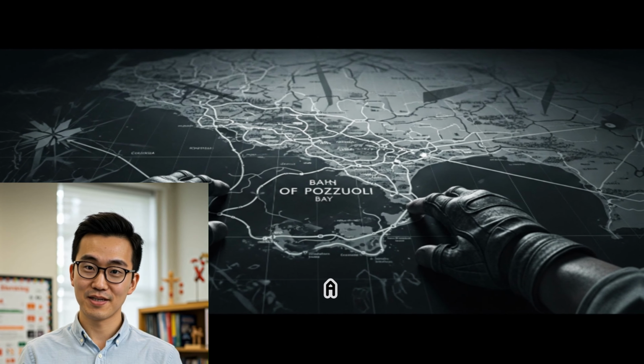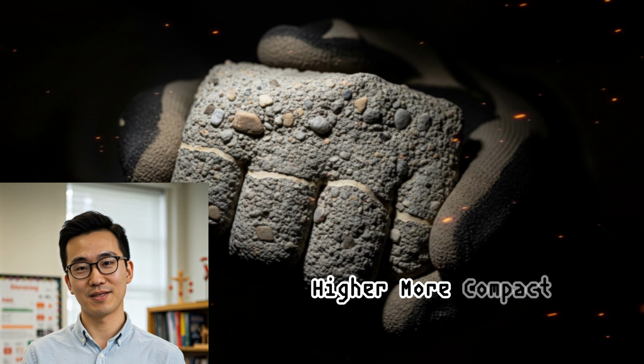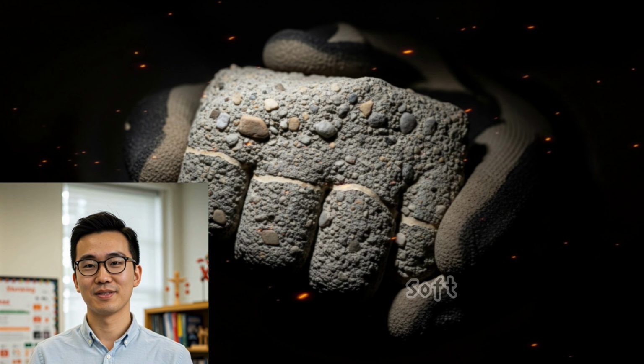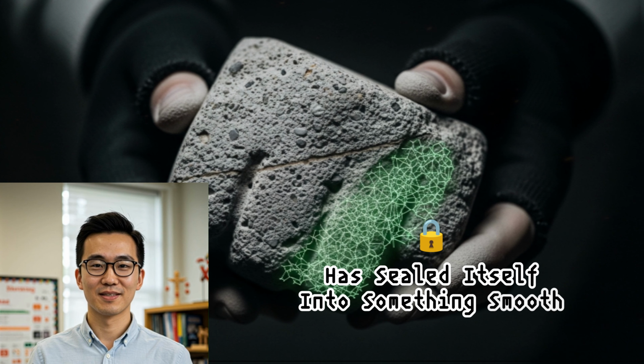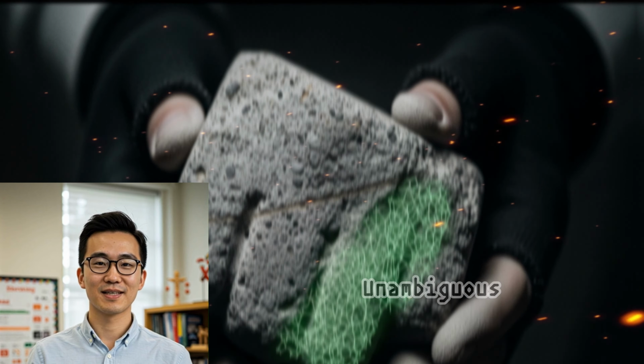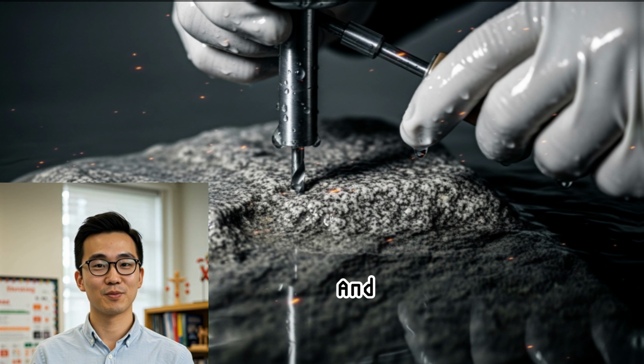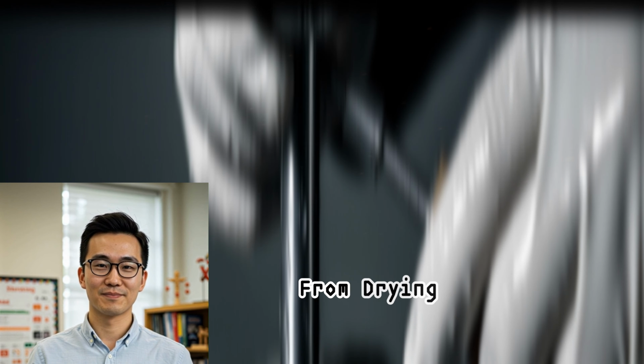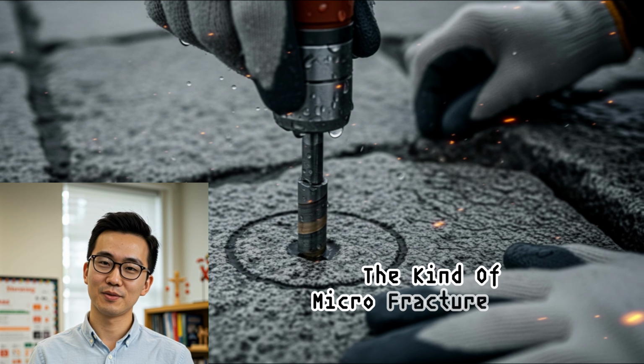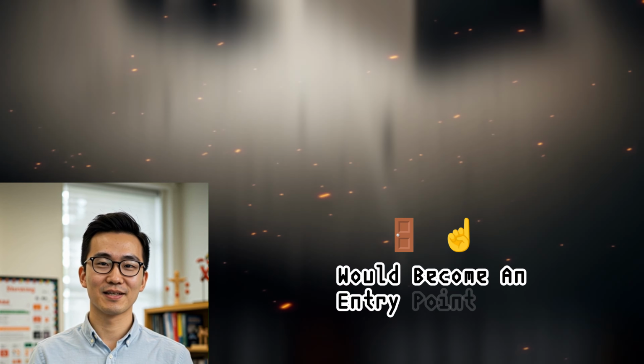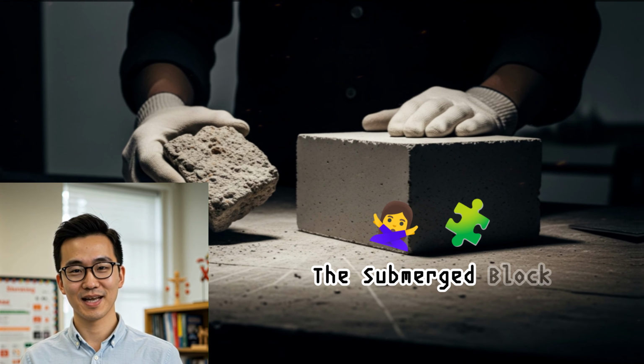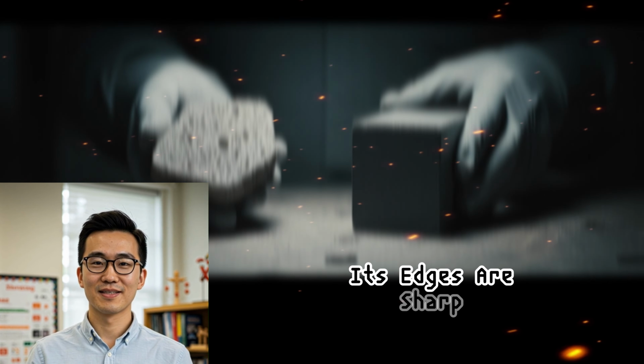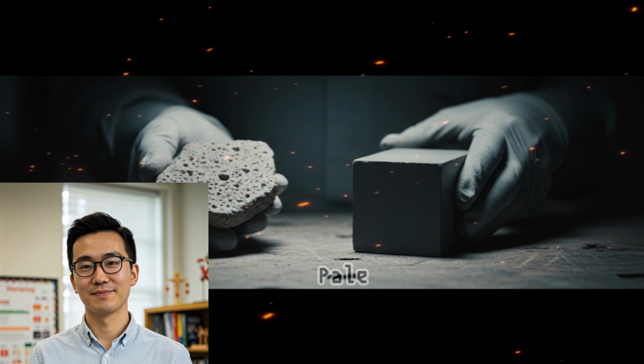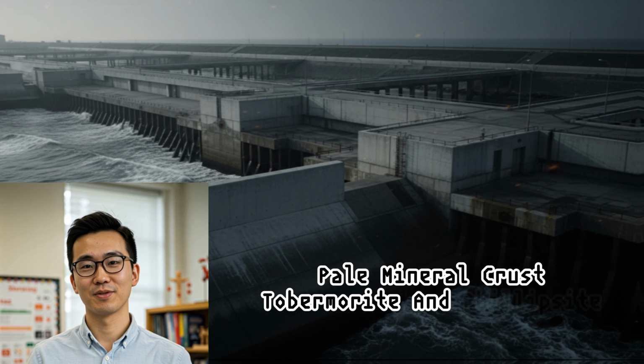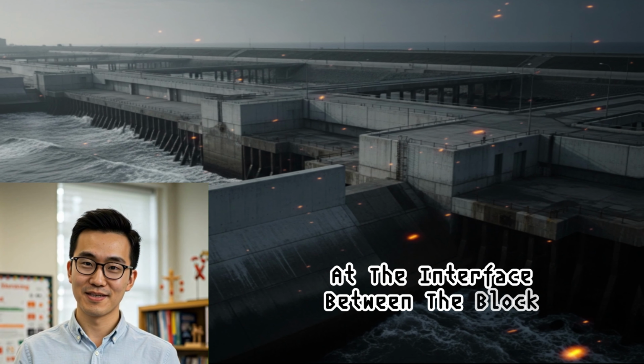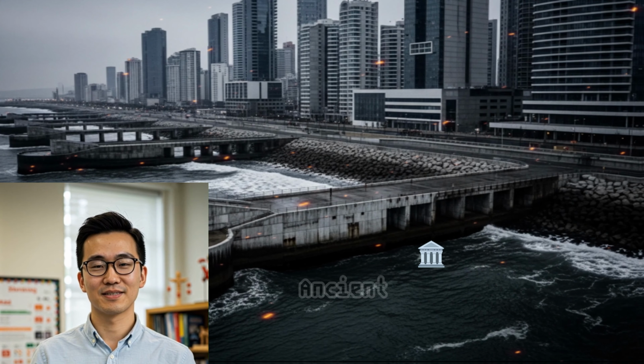Tapping it with a knuckle produces a different pitch. Higher, more compact, less hollow. The surface that was soft has sealed itself into something smooth. At 90 days, the comparison is unambiguous. The air-cured block is strong and serviceable, but carries a small surface crack from drying shrinkage. The kind of microfracture that, in a marine environment, would become an entry point for saltwater attack. The submerged block has no cracks. Its edges are sharp. And across its surface, there's a faint pale mineral crust, tobermorite and philipsite, forming at the interface between the block and the water, exactly as they do in the ancient harbour walls.